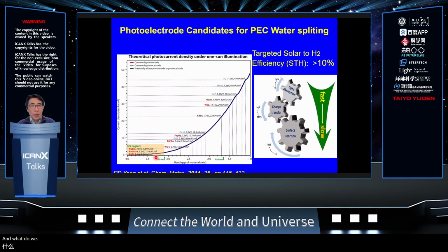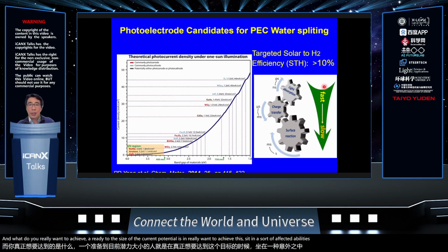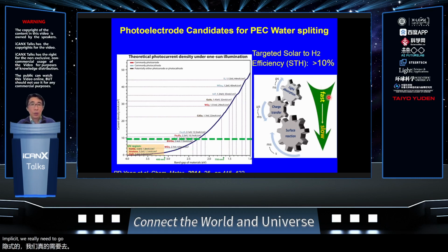What we really want is to use our knowledge in material design and semiconductor design to improve the abundant metal oxide-based materials. In particular, as we said, this is the bottleneck on the photoanode side. And why are we choosing metal oxide? Because they are cheap, most of them are quite low cost, and also stable compared with other semiconductors. What we really want is to achieve a relatively high photocurrent. For example, if we want to achieve a solar-to-hydrogen conversion efficiency of 10%, we really need to reach around this range.